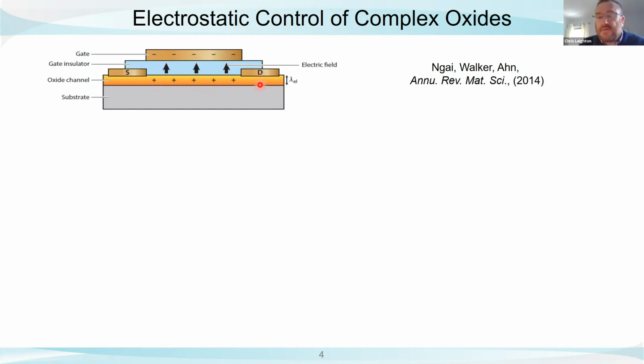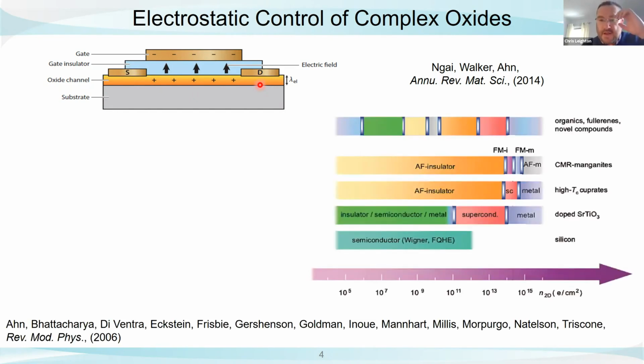So what's wrong with just taking that very simple principle and trying to apply it to a material like a magnetic complex oxide? Well, if I take something like the phase diagram of that manganite that I just showed you, and I project it onto a two-dimensional charge axis, then it turns out that to be able to tune across the entire phase diagram, we would need something like 10 to the 15 holes per square centimeter.